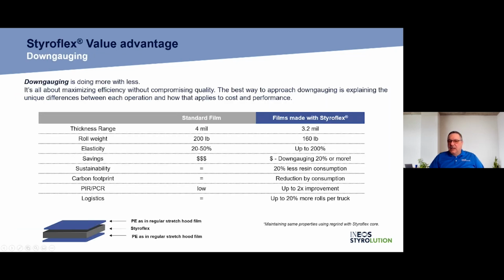As you can see here, down gauging offers a better opportunity for a good film. So what we did here is we compared a typical 4 mil standard olefin-based film to a 3.2 mil Styroflex-based film. As you can see here, a typical 4 mil film would weigh up to about 200 pounds, whereas a Styroflex film would be a 160-pound roll. Its elasticity on a base 4 mil film would be 20 to 50%, whereas Styroflex would be up to 200%. Thus, the reason for having a much thinner and smaller roll for the stretch hood application. Because of the down gauging of the film, there is also a cost savings.